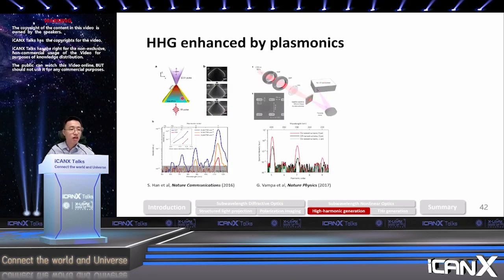Because of that, people have been thinking about whether we can increase the high harmonic generation at the surface of the material, for example, by using plasmonic nanostructures. But later they found that one of the biggest issues of using plasmonic nano antennas is that these nanostructures have very, very low laser damage thresholds, up to tens of gigawatts per centimeter squared peak intensity, and then they get burned or just melted.